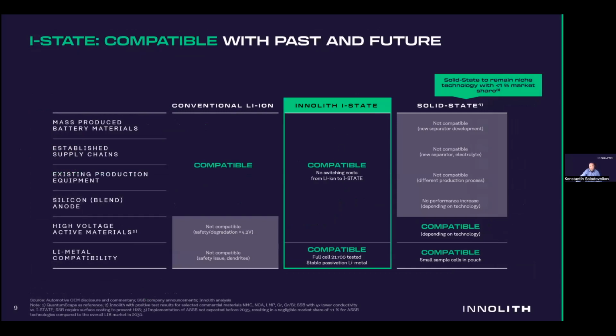To illustrate why we believe that in terms of manufacturability we would have an advantage, you can see on this slide that we can produce our technology, which is in the middle, compared to conventional lithium-ion exactly in the same equipment, using supply chains and materials which are used today by the industry. So switching cost would be minimum, plus our technology can work with silicon. We have ongoing development of new technologies with silicon for higher charge and discharge, but unfortunately it comes with a trade-off of cycle life most of the time.